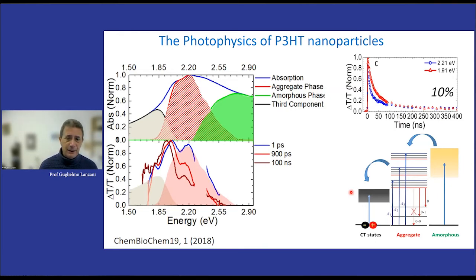The other interesting thing is that if you measure up to almost half a microsecond, you see that there is 10% of the excited state population that survives for a very long time. Here, after 400 nanoseconds, all the singlet excited states are gone for sure.